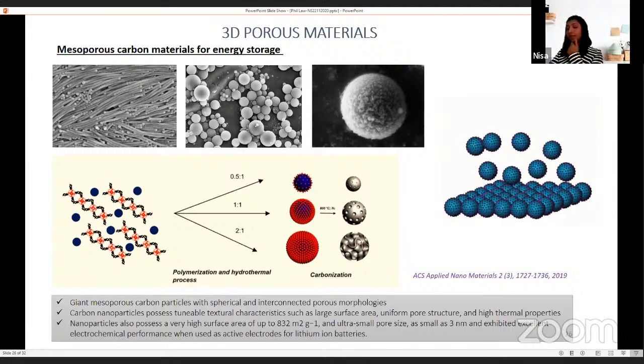So in this particular study, we followed a soft templating process by using block polymers. Here the target was to make tunable carbon nanospheres with uniform porous structures. So you can see that the pure block polymer exhibits rod-like features, but as the reaction proceeds, the morphology was changing from the thread-like features to spherical-like features. And we use these carbon materials as electrodes for demonstrating energy storage applications.